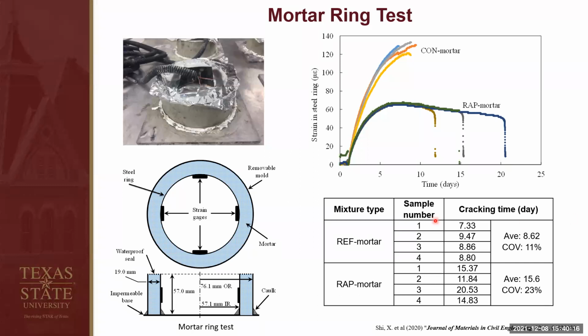Here we are only using mortar samples because concrete samples take a lot of time to crack. So we developed a smaller sized ring geometry, which enables us to have a much sooner cracking time for the cementitious material.